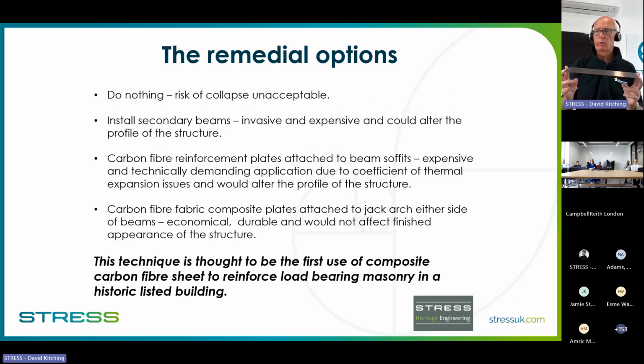But the problem is if you reduce the temperature down to where you need it with cast iron, the glue, the adhesive that you use to bond this to the cast iron, it would never cure until you got up to a temperature where the cast iron had expanded again, and really you'd have just stuck that to the underside of it. Wouldn't do any good. It's no good in shear, so when that cast iron shears, that's no good because it would just debond. So we got to think again, and we came across a method of using carbon fiber fabric, but you don't use it on the beam, you use it on the brickwork.